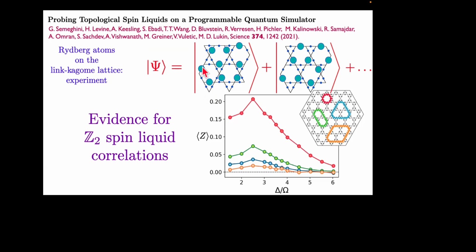So they like to spread themselves out. That's very much like the dimers, which are close packed, but they can't overlap. So there's a very simple mapping between the Rydberg states and a dimer covering of the Kagome lattice. These big circles form a dimer covering of the Kagome lattice. There's some evidence from the observations. This is a relatively small system, and there are various issues with equilibration and so on. But they do see some evidence that the ground state has many such configurations. I don't think it's conclusive yet in terms of a Z2 spin liquid, but it's very exciting because here you can actually measure local observables in a way that you can't in neutron scattering in the other material I showed you.